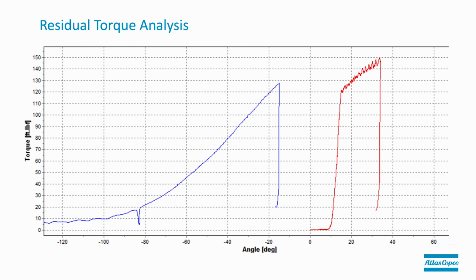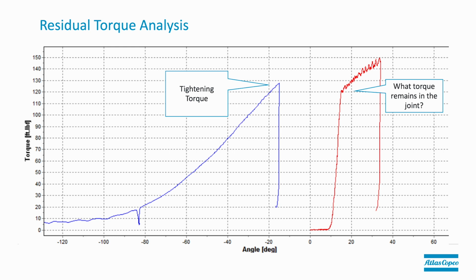So this is a picture of two different traces. I want to be clear we're talking about the tightening torque that we put into this joint, and then the red curve here is after the fact. We're coming back and we're retightening this joint in the tightening direction, and we're looking for the torque that is maintained in the joint. So we can see the scale and angle and how wide these are. We get a nice linear elastic tightening curve on the blue here where we hit our torque dynamically, and then after the fact we come back and we create this curve where we've tightened the bolt in the tightening direction, and we can see that breakover point. That's the point we want to look at and ask the question, what torque remains in the joint?